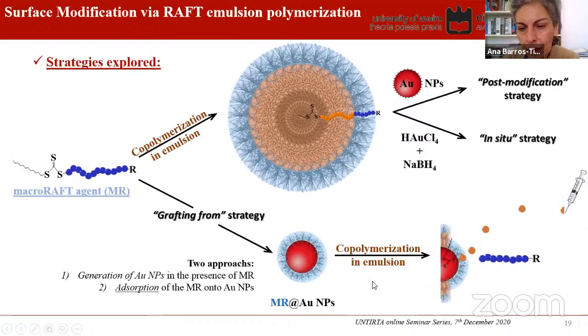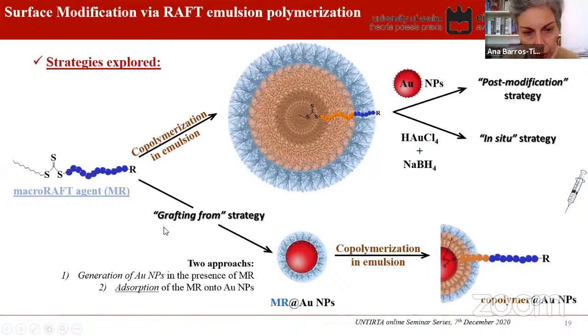So we, as I said, focused on this second approach, the grafting from approach. But we first started by preparing the macro RAFT agent, which from now onwards will be designated as MR, carried out the copolymerization in emulsion polymerization, and then added the gold nanoparticles, and we call this a post-modification strategy. Also, this copolymer prepared by RAFT in emulsion was also used for this in situ preparation of the gold nanoparticles by adding the gold precursor followed by the reduction and formation of the gold nanoparticles.